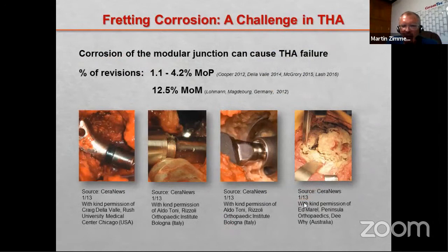If you look in the recent literature about the occurrence of fretting corrosion in vivo, following the different publications, we can have up to 4.2% of revision with metal-on-polyethylene articulation specifically due to fretting and corrosion. It was a much higher rate with metal-on-metal, due also to the fact that metal-on-metal creates these ion aspects and the interaction between the femoral ball head and the taper of the stem.